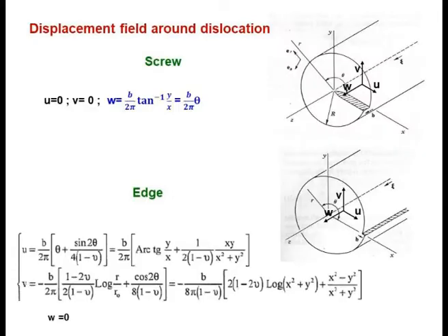But this vector r which we have defined, as I said, is a displacement vector. So if you take a dislocation, the Burgers vector is what we define as the defect vector. But if you look around the screw dislocation, there is a gradual variation of the atomic displacement around the line direction, and that is given by these terms, correct? And this is called the displacement field. Similarly, for an edge dislocation also we have this expression, all these expressions he had also mentioned.